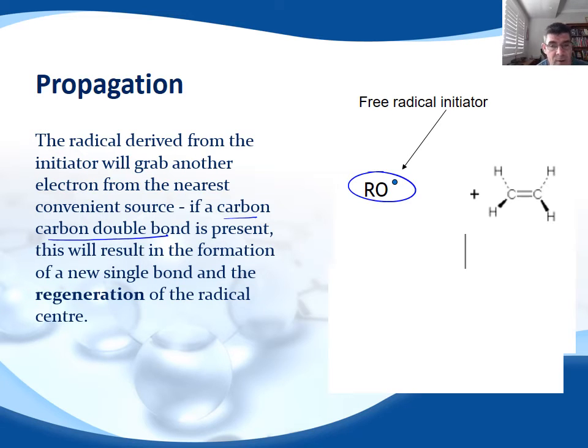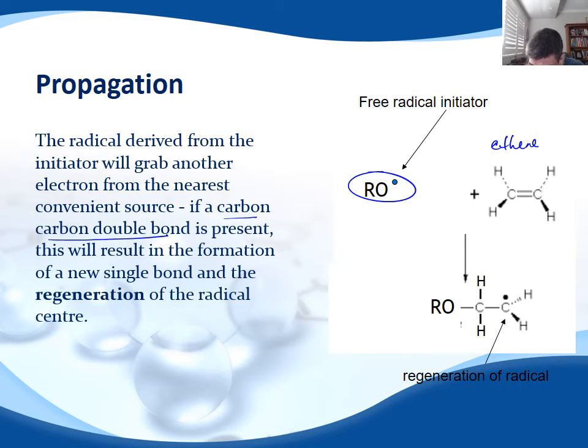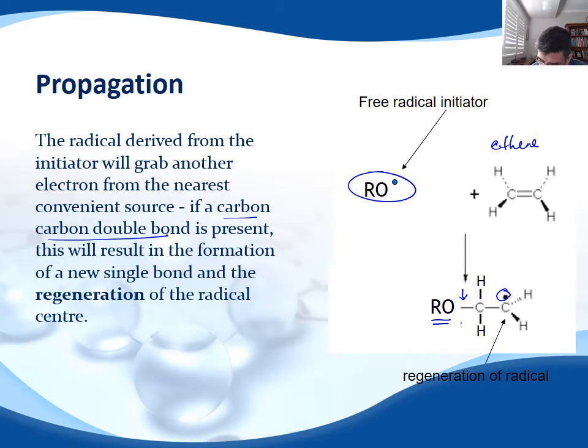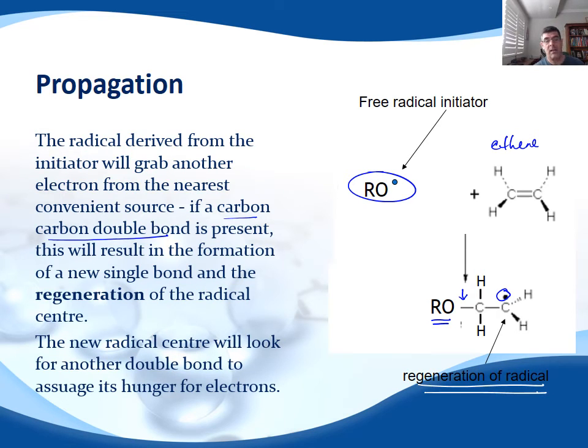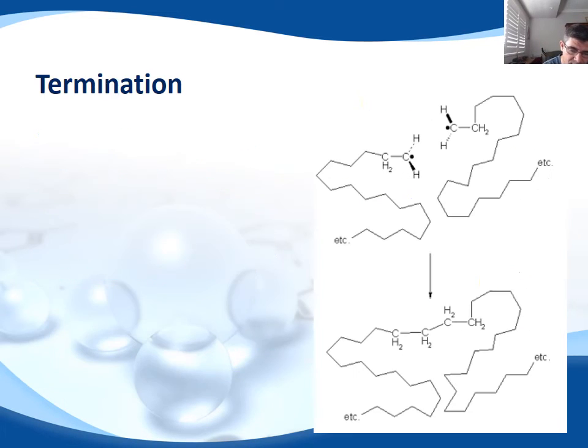Here's our free radical from the organic peroxide, and here is our ethene. What's going to happen is that the free radical bonds to one of the electrons from the carbon, but the other electron is now unbonded — so it itself has become a free radical. This carbon here is the regeneration of the radical. All we've done is pass that one unbonded electron from the initiator to the actual monomer itself. That's just as unstable, so this electron is going to look for a second one to bond with, finding another double-bonded carbon to do the same thing — and so growth occurs.